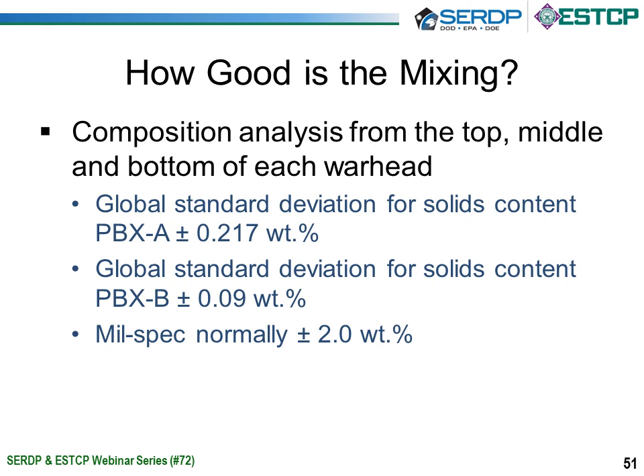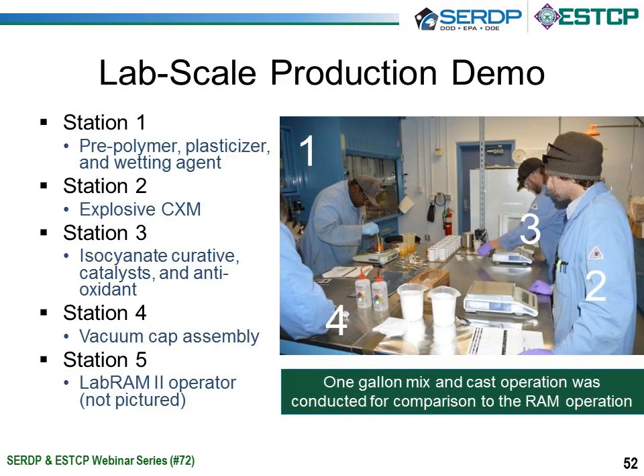And just for perspective, the mil spec for both of these materials allows for plus or minus 2 weight percent of the total solid. So we're getting very, very good mixing, very, very homogeneous dispersion of the solids within the binder ingredients, even at very, very rapid mix times. If we're moving on to slide 52, what we did under this ESTCP program is we did a lab-scale production demo using the LabRAM 2 as the mixer.